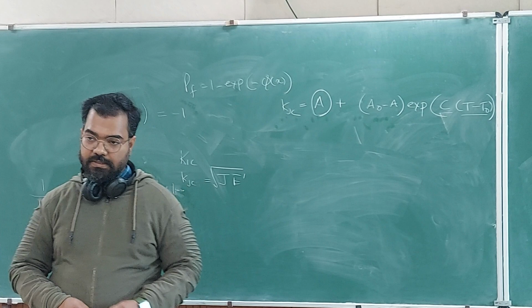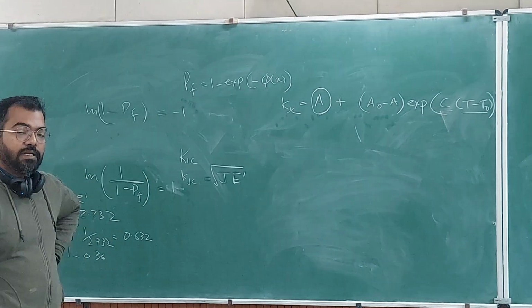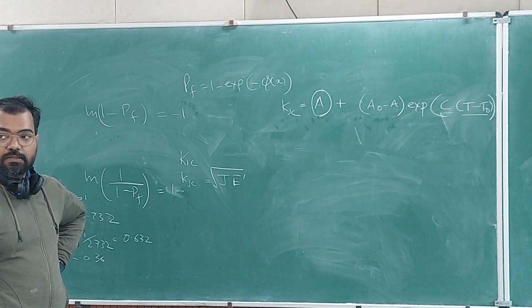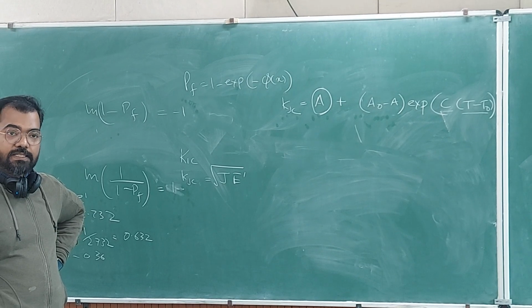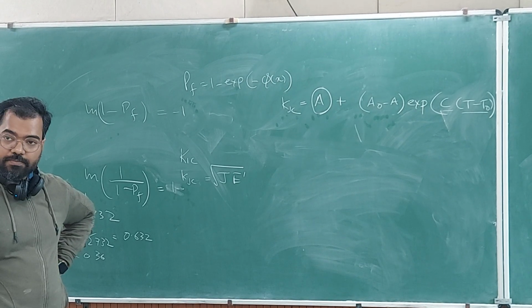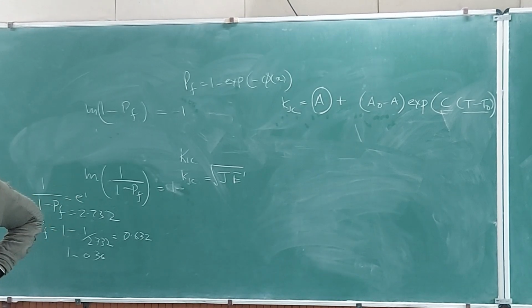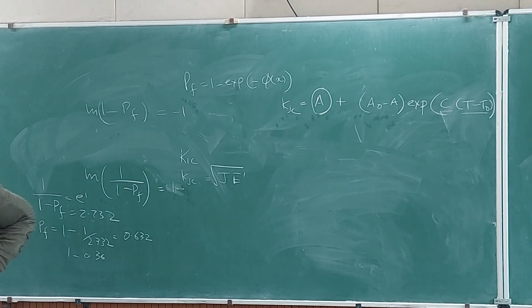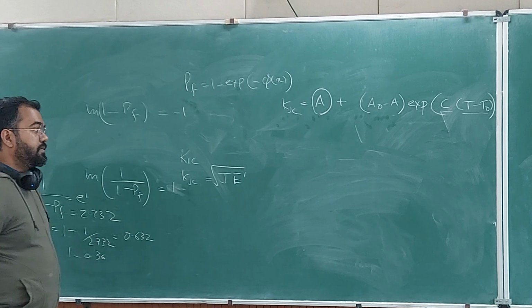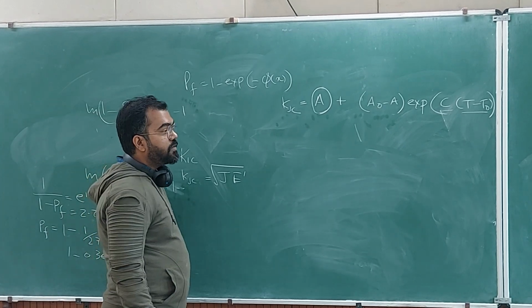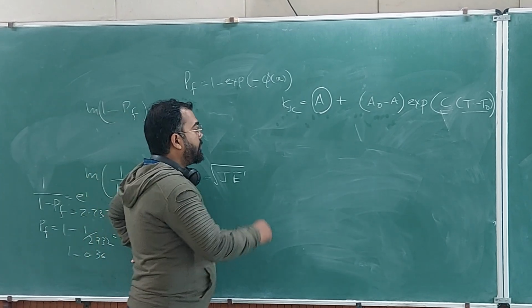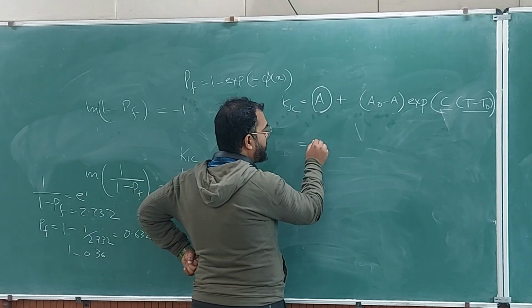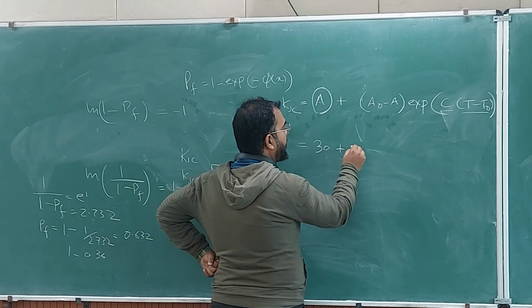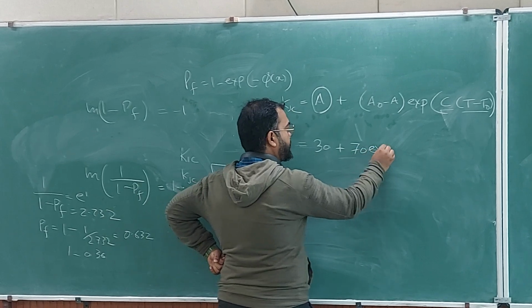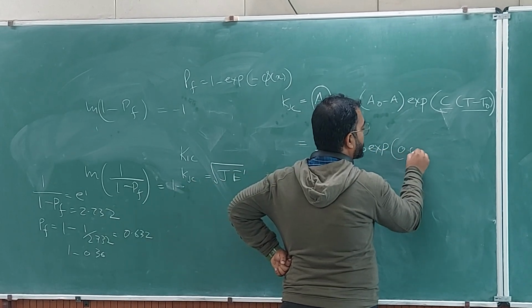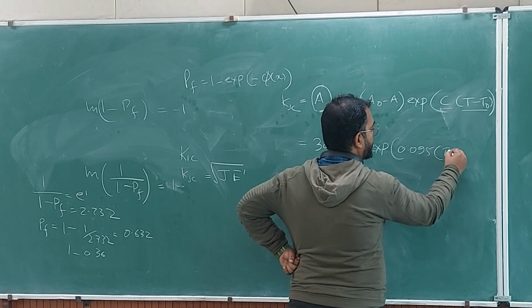A lot of testing and data analysis has been done on ferritic steels, and maximum likelihood analysis has been performed on ferritic steel, especially for reactor pressure vessel steels. In those ferritic steels, most of them have a value of A equal to 30, and then you have 0.095 (T minus T naught).